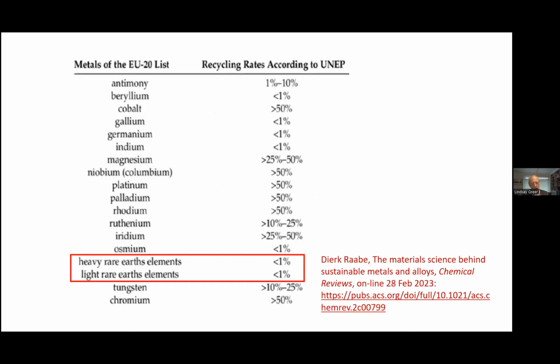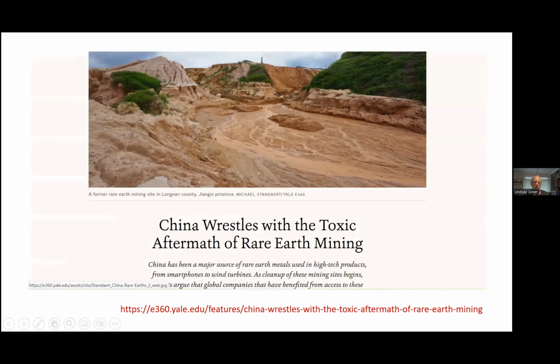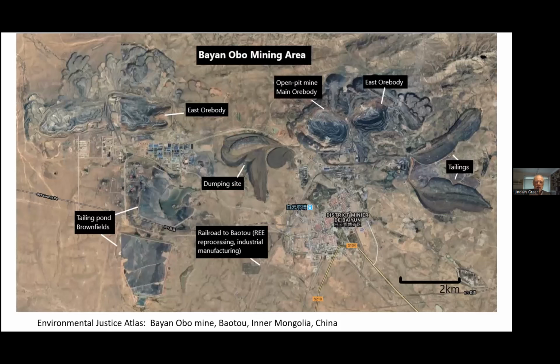Horrifying is that common metals like aluminium and steel are quite well recycled. Metals on critical lists, some of them are moderately well recycled, like the noble metals, platinum, palladium, but the rare earths are hardly recycled at all. So there's a gross failing. Of course, recycling them is very difficult because you don't have components made out just of rare earths. They would be typically rather small doping amounts in something else. So it'd be rather hard to recycle them, but we really must improve that. And of course, there's concern about the local environmental hazards. China has stopped some mines altogether. Here's the main source of rare earths at present.